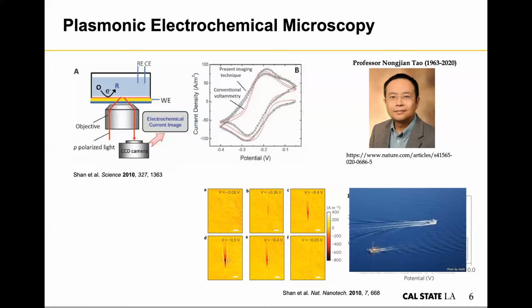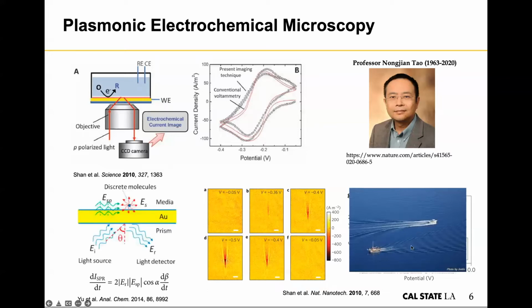So this long tail behind each particle is very important for you to be able to identify the particle being there. At the same time, the intensity of the tail also gives you information about how big the particle is. There's definitely a drawback: if you have a lot of particles on the surface, the tails could interfere with each other. And a colleague from Dr. Tao's group actually developed mathematical methods to deconvolute the overlaying of different tails. Now, this is a general idea of how the tails are generated.